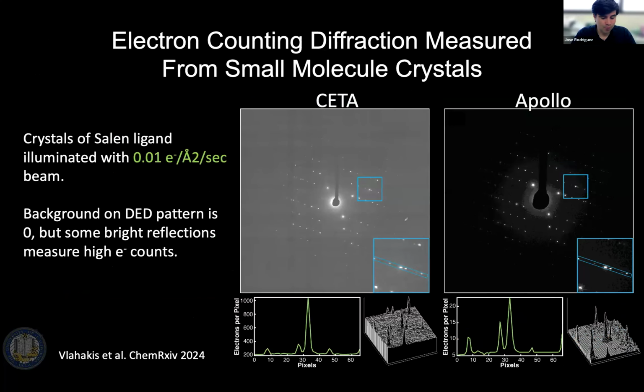That's a challenge for diffraction, more so than for other methods, perhaps, because while for single particle and tomography the signal is spread out evenly across the detector, here you have signal concentrated at very, very strong reflections, right? All of the signal is coming into those reflections at the same time. And so there isn't necessarily a direct relationship between the incident fluence on a sample and the amount of signal that might end up on any given pixel. Here I'm giving you an example of crystals of a particular small molecule Salen ligand illuminated with a very, very low dose of electrons, 0.01 electrons per angstrom squared per second. And there are patterns on the right-hand side showing what you would observe with a conventional scintillation-based detector, CETA, and then with the Apollo.